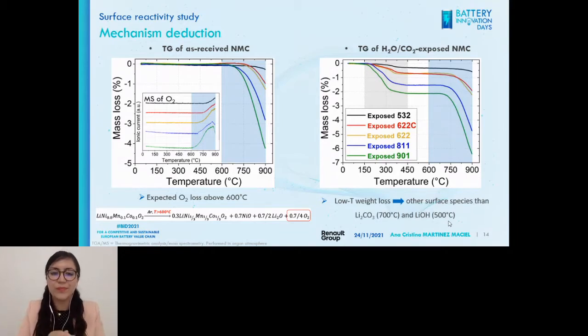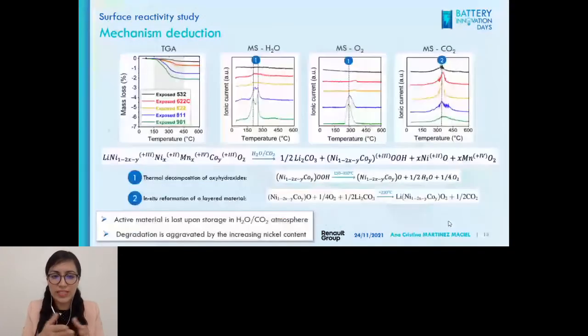For that, in the next slide, I'm showing the mass spectrometry results of this temperature range. What we can see here is that we are seeing a production of water, oxygen, and CO2. After some calculations of this specific part of the spectra, we were able to deduce this equation, which shows how the NMC materials decompose upon water and CO2 exposure.